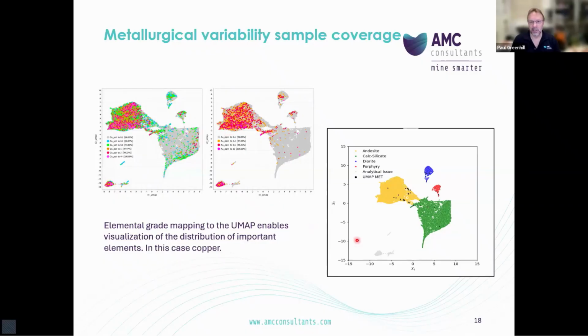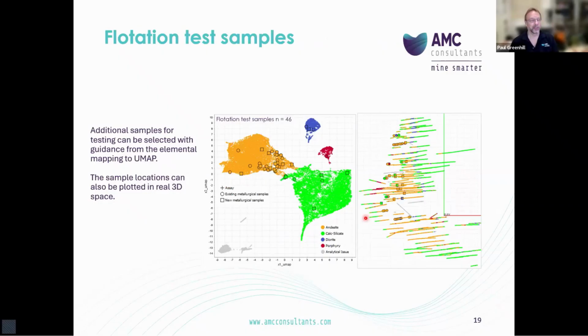And you can see when we look at the UMAP on the bottom right, where we've projected the metallurgical samples, plotted as the black dots, and I hope you can see them, they're relatively small, you can see, in fact, that there is quite a discrepancy between where those samples have been selected and where there are other significant copper grades that should be tested in the metallurgical program. So again, the tool allows us to make suggestions, select additional samples. And here what we've shown is suggested additional samples in the square symbols that allows us to expand the metallurgical data set.